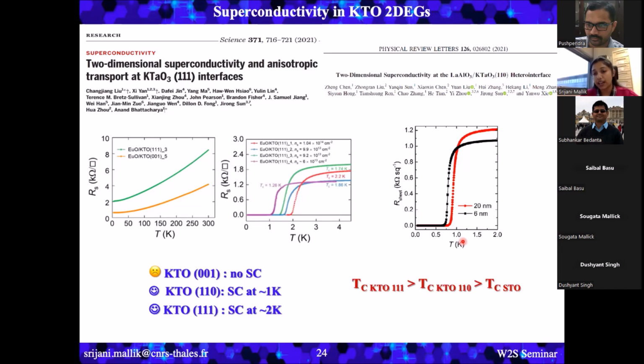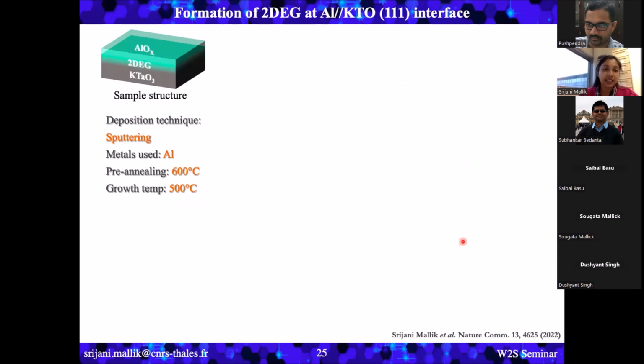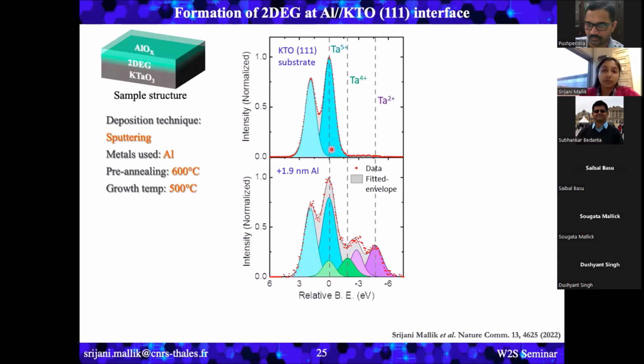So what we tried is again the same technique of growing aluminium using DC sputtering, on KTaO3 (111) this time. And when we did the in situ XPS, again we found that before depositing anything, the KTaO3 (111) substrate is showing only the tantalum 5+ state. But as we start depositing aluminium on top of this, we could get tantalum 4+ and tantalum 2+. This means that oxygen vacancies are created.